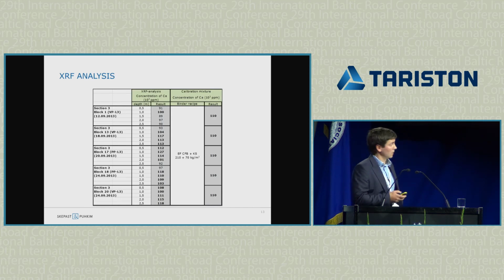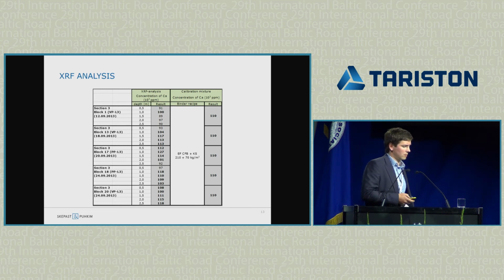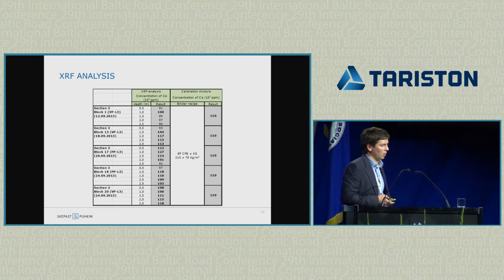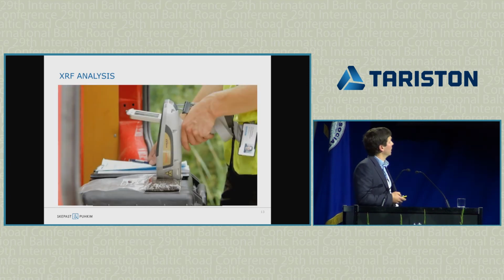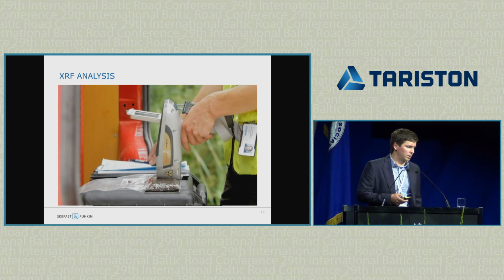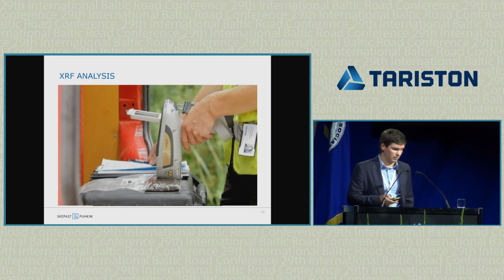So XRF means that we had a calibration mixture prepared in laboratory with the optimal and ideal content of calcium in it, and we took several material samples from the site after the mass stabilization mixture was done, and we measured the concentration of calcium, and the purpose was to get numbers as close as possible. So you can see that they were quite close enough, and this is just one example of the results. We have a long list of them. And the method was very simple. It was done with portable machinery on site, a very fast and effective way to find out the results.